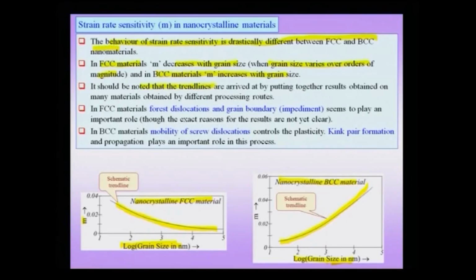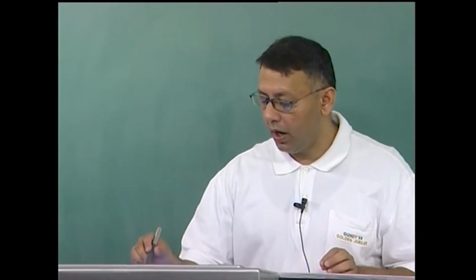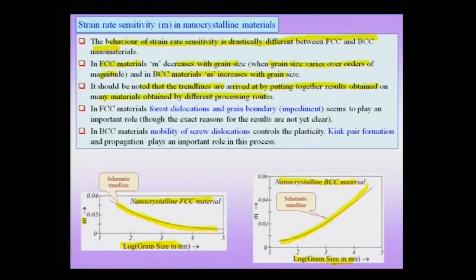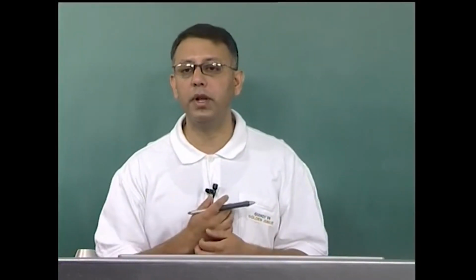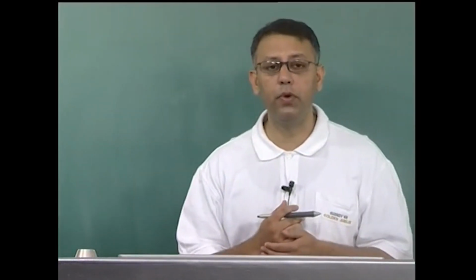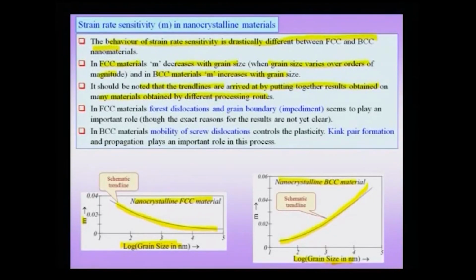And you should note that the trend lines which we have seen below are not exactly followed for one material or one testing condition. They are arrived at by putting together results obtained in many materials, and these are obtained through many processing routes. We have already seen the important property differences which can come from the processing route itself. We had noticed, for instance, how different in properties electro-deposited nickel can be from a powder consolidated nickel. So, we have seen that the processing route can have a profound influence on the properties, and therefore, when we see such trend lines, we have to keep that at the back of the mind.